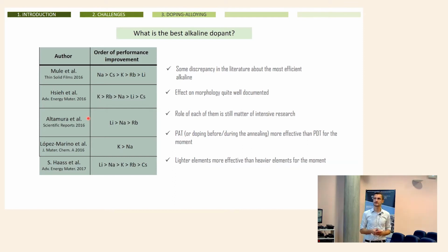For example, for sodium, the theory is that when you synthesize your material at high temperature, sodium occupies the copper position. Then when you cool down your material, this sodium is not soluble anymore in your solid, and then migrates toward the grain boundaries. And then keeps a copper vacancy. And these copper vacancies are the ones that control the p-type conductivity. So the use of this alkaline is really very important for controlling the conductivity of your material.